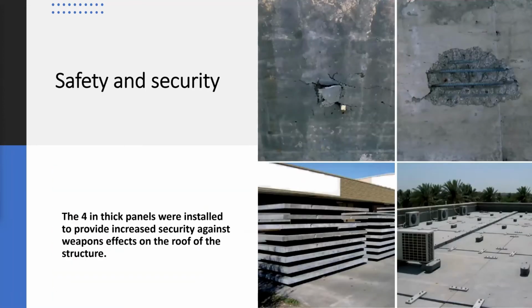Another application, which is pretty niche, is safety and security. The 4-inch panels were installed to provide increased security against weapons effects on the roof of the structure. On the bottom pictures, you can see that the panels of UHPC are extremely thin compared to conventional concrete, and they provide roughly the same security. On the upper right-hand side, we could see that the reinforced concrete and the UHPC both sustain a blast at about the same distance. And the UHPC on the left-hand side is in much better shape versus the conventional concrete on the right-hand side.